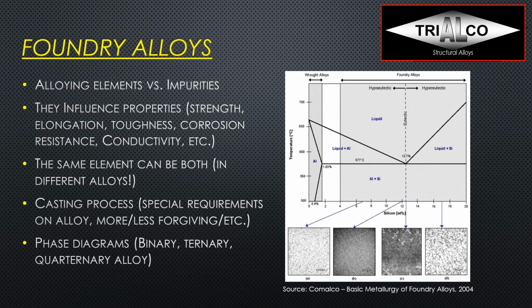So here we can see the aluminum silicon phase diagram just between 0 and 20% silicon, which is where most of our alloys are. So we distinguish on top of the line, we have the liquid phase. We see the eutectic point at 12.7% silicon. Below the liquid and to the left of the eutectic, we will find liquid and aluminum. To the right, in the same triangle, we find liquid and silicon that solidifies first. If we fall below the 577C line, where the eutectic liquid is all frozen, we find aluminum and silicon, and this time now it's all solid.